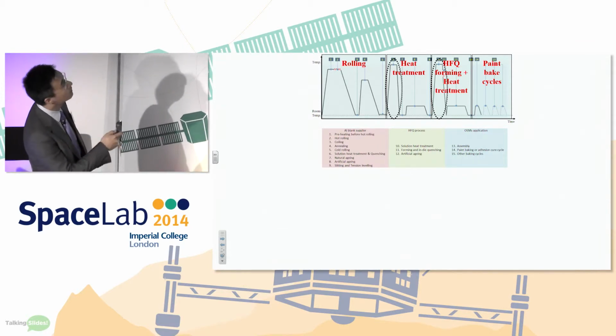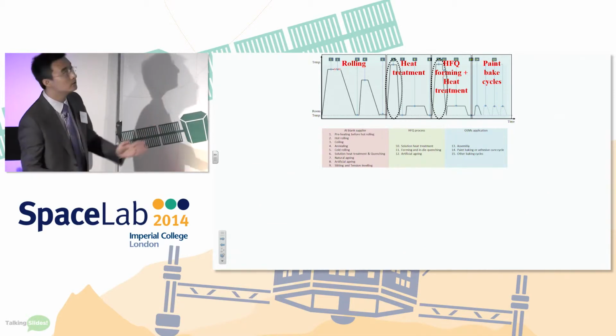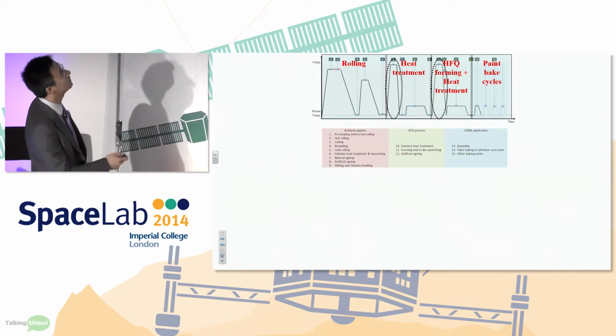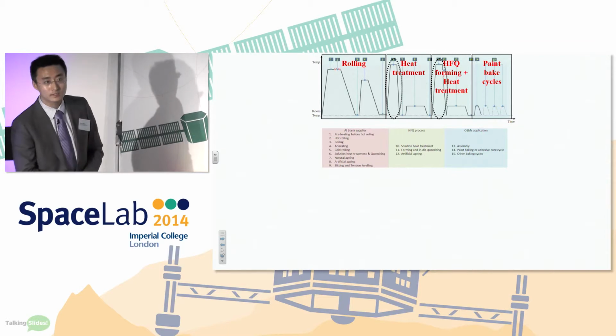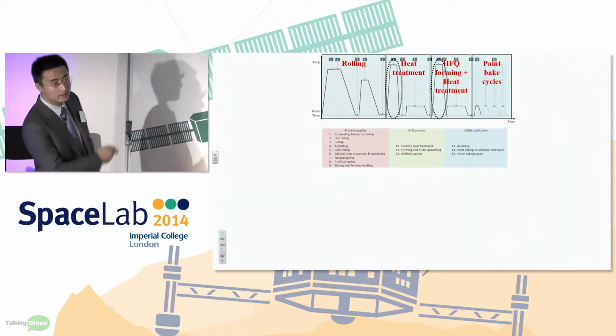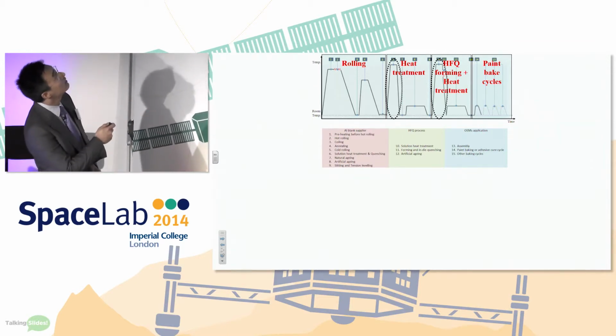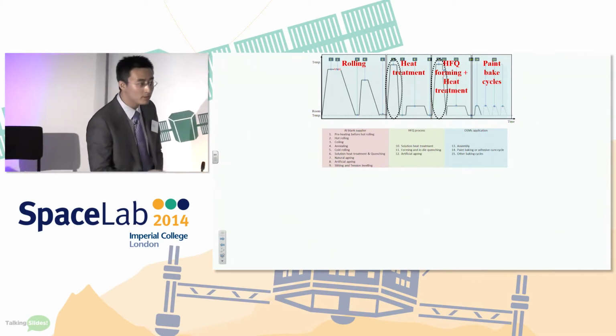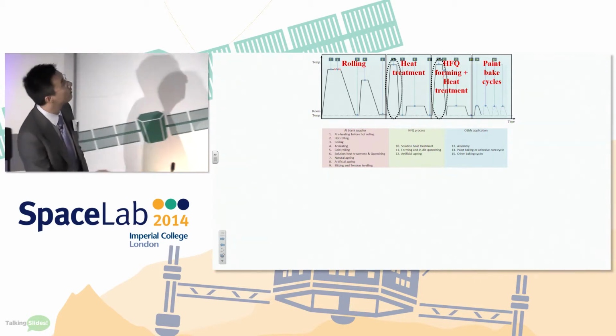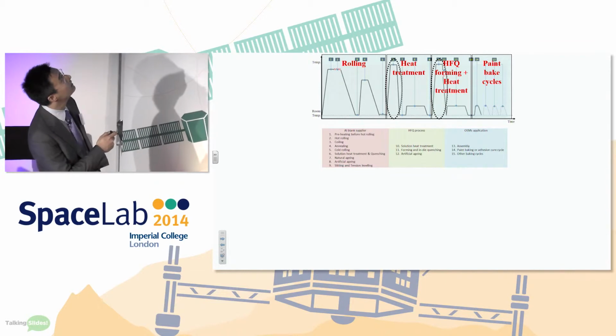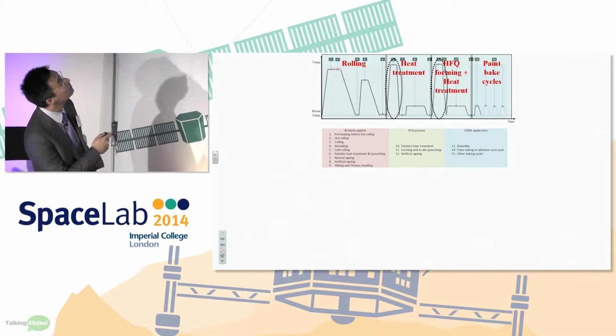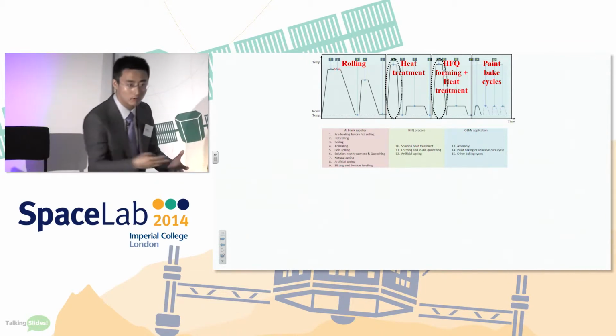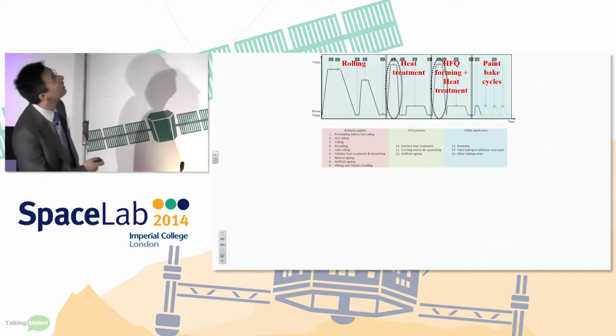And this graph shows the temperature evolution during the HFQ forming process. The x-axis is the time. The y-axis is the temperature. So the aluminum blanks are normally provided by the material producer by hot rolling. So you can see this is the temperature. At very high temperature, they roll the aluminum ingot into a sheet blank.